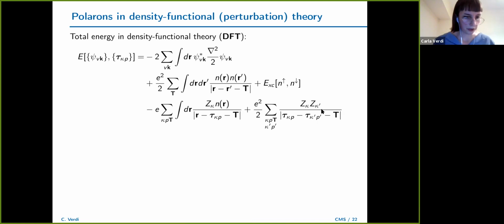So what people do in DFT if they want to calculate polarons is that they take a supercell, they add an electron, or they take one out if they want to study a hole polaron. But let's say they add one electron, and then they can relax their supercell configuration and see if they achieve a solution where the ions are a bit displaced and the electron wave function is localized. This is done a lot in the literature, but it has some serious problems.